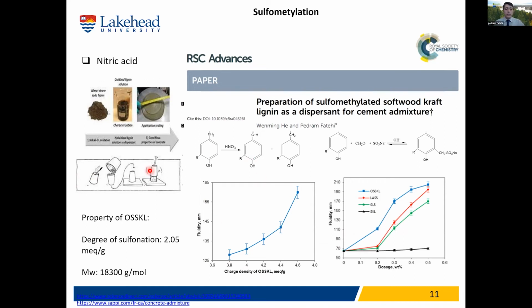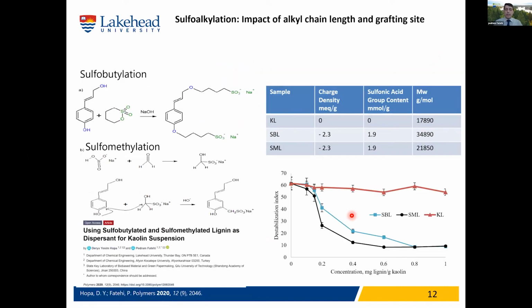So what is fluidity? For fluidity, you make a mixture or paste of the cement, you put it in this cone, and then you pull up this cone, and you let the paste spread, and that's called the slump test. And then you measure the diameter of the circle that's generated. And the larger the diameter, the higher the fluidity. And that's very important for workability of the cement. And it's an indicator of the rheology and viscosity of the suspension. So the point is that we generated the samples, and they work really great.